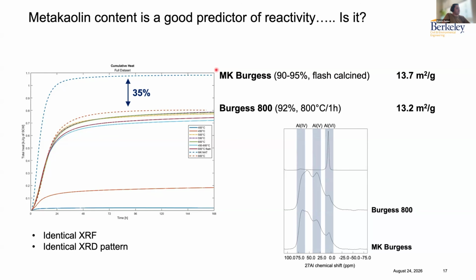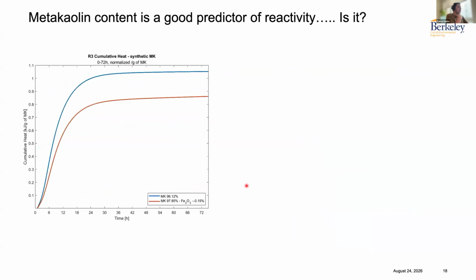So it's quite puzzling to have these two materials with such a different reactivity, essentially exhibiting the same bulk chemical composition. So not trying to scare anyone about calcined clay here, but just trying to highlight that there is still a lot of things that we don't fully understand in terms of SCM chemistry and where reactivity is stemming from.